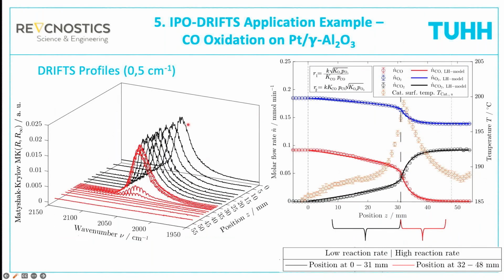And now we can drive through the reactor and we can measure the profiles of the adsorbed CO. And you can now easily understand why the profiles in the reactor look the way they do. In this first zone where we have this low and almost constant reactivity, you see that the platinum surface is basically covered with CO. So there are very few sites available for reaction. And only if the temperature reaches high enough values, then some of the CO starts to desorb and we free sites, and then oxygen can adsorb and the reaction picks up speed. And we have this transition here to a first order kinetics.